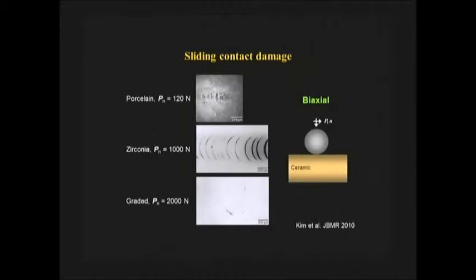And I'm now going to move on to the last topic I'm going to cover, the sliding damage resistance. Remember, I spent so much time on sliding on a surface. It's so easy to initiate the crack and much more aggressive to propagate the crack. Now, if you slide on a surface, this is a piece of porcelain, 120 Newton, massive cracks form on the surface. You see those cracks, like herringbone cracks, like those herringbone fish scales. And in fact, if you cut across or look on the side, I should really show you a picture. It is what we call distorted cone cracks, the partial cone cracks, the little tails there.